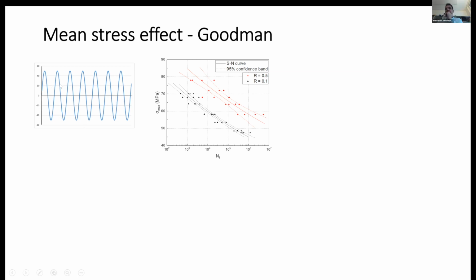So what are the parameters of the fatigue loading? We have the maximum stress, as we defined before, which is what we report here. We have the stress amplitude, which is from the mean to the maximum. We have the delta stress, the stress range from maximum to minimum. We have the mean stress, the average stress. We have the frequency of the loading. If we change the mean stress, the load that we see here has a mean stress of 0, which means that it is reverse loading from positive to negative. In this case, it goes from plus 45 to minus 45 MPa.